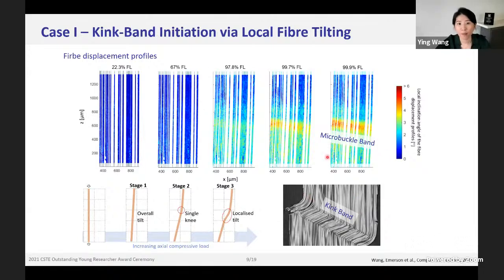Even at 99.9% of the failure load, this microbuckling band is still much shallower, the angle of the fiber is much shallower, and the bandwidth is much narrower compared with the kink band. But we did see the nucleation of fiber microbuckling from one single kink up to a localized tilting region, where we established a schematic here.